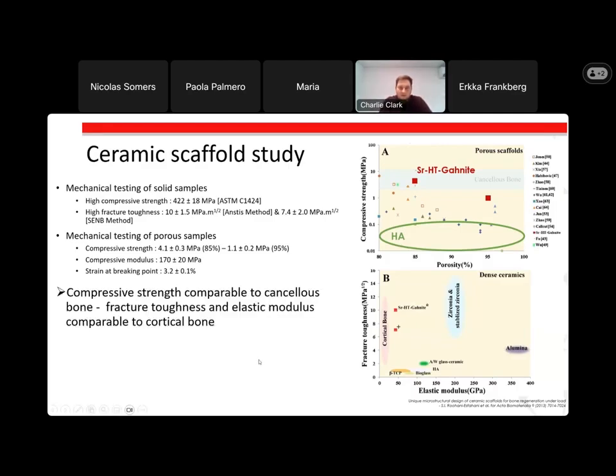So what we can see is that the compressive strength is comparable to the cancellous bone. The cancellous bone is the porous bone that's in the middle of a human bone. Whereas the fracture toughness and the elastic modulus are more comparable to the cortical bone, which is to say the solid, dense exterior of a human bone. And when we're looking at the cancellous bone, hydroxyapatite, for instance, does not have a compressive strength that's similar to cancellous bone. We're almost 10 times or 100 times worse off.